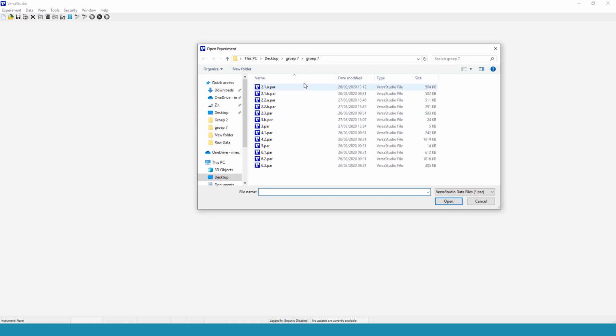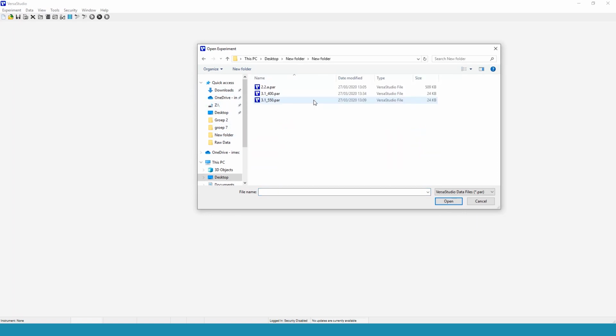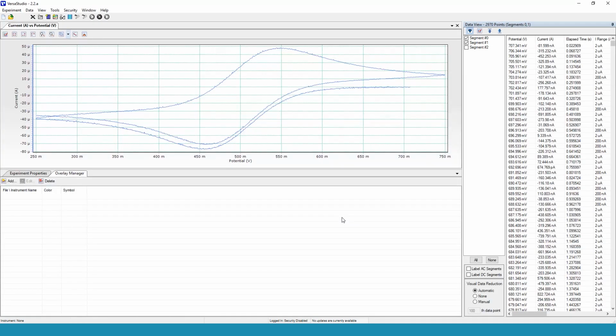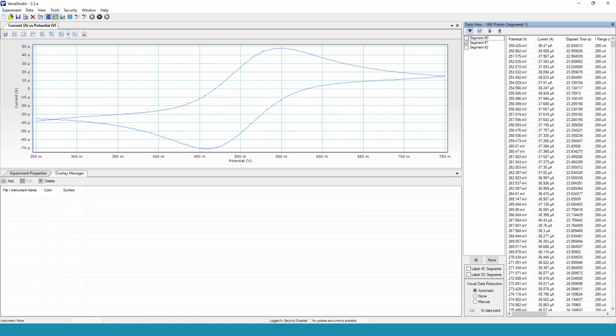As explained in the guideline, for that we will choose two potentials based on the IV curve from section 2, practical part 2. So if we look at that data, in this case, we can clearly see that maybe before the cathodic peak and after the cathodic peak, we could take, for instance, around 550 and 400 millivolts for the chronoamperometry experiment. So now that we have chosen these potentials, we are ready to set our chronoamperometry experiment.